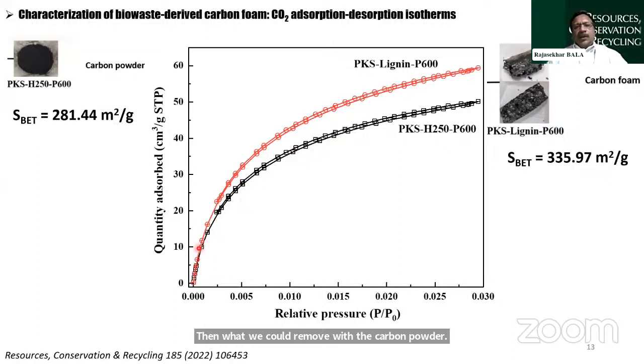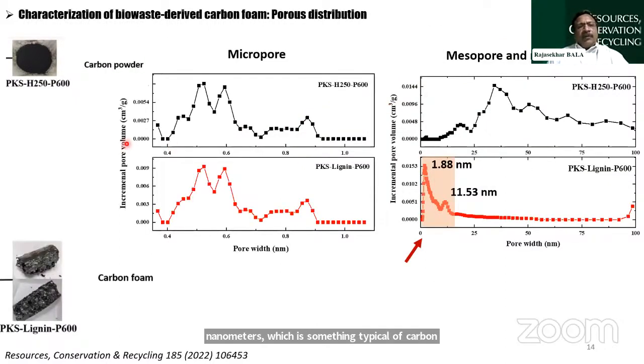In chemistry, we call this more like an Type I isotherm. There's an adsorption capacity as to how much CO2 is removed and retained on the surface. This type I isotherm is indicative of the presence of micropores, meaning pores with a diameter of less than 1 nanometer, which is typical of the carbon foam that we have over here. All right, to provide further evidence of the multi-porous structure of carbon foam, you could see all the pores we have. Again, I don't want to go into details, but what I would like to highlight here is that you could see less than 1 nanometer. These are the micropores that we have in our carbon foam. These micropores play an important role in sequestering carbon dioxide and retaining it onto the surface through diffusion, followed by adsorption.